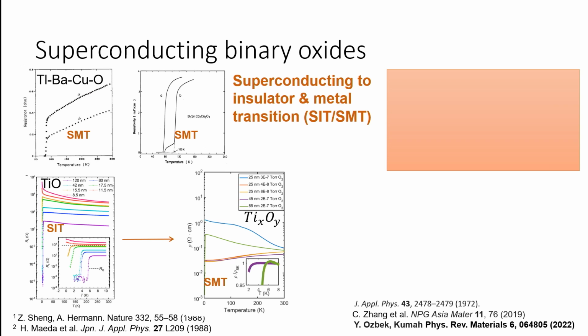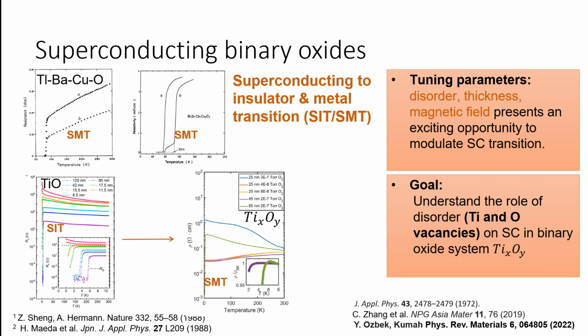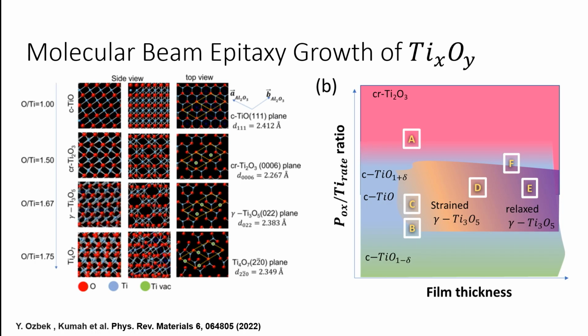But one thing we also found is that under certain conditions, we can get films which are metallic and show a drop in the resistivity down to the lowest temperatures that we can measure in my lab. So one of the things we like to do is understand whether disorder plays a role in this semiconducting state. And if we can suppress disorder, then we can probably engineer superconductivity to high temperatures in the system. In the interest of time, I'll skip this to say that depending on the oxygen concentration, the cubic phase can accommodate up to 25% oxygen vacancies without changing the structure much. But you can also engineer the oxygen ratio during the growth to get a wide range of other different phases.